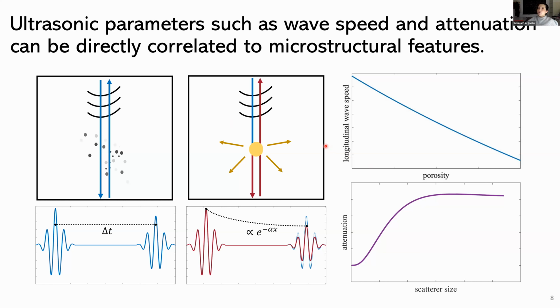So essentially, although I'm not getting a direct reflection from the feature that is in this propagation path, I know that my wave is going to lose more energy as it propagates through a volume where there are localized features that wouldn't necessarily affect the wave speed directly, but that are definitely impacting the scattering and the absorption of that wave as it propagates through.